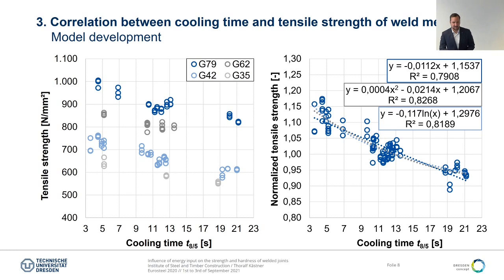Why 12 seconds? As you can see on the left side, this is the field where we have the largest amount of results. And what we can see is that we can describe this behavior with different mathematical functions: with a logarithmic function, with a linear function, and also with a quadratic function. And all of these functions show a more or less good correlation.